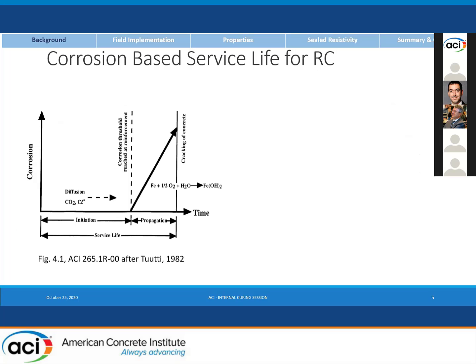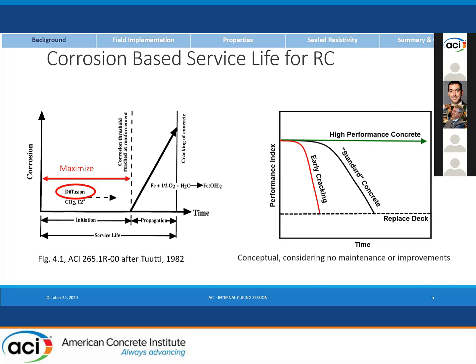So just to set the stage a little bit of what I'm talking about when I say service life, really I'm focused on corrosion-based service life. So we're going to be really primarily talking about extending the diffusion portion of the simplified model, where we have just an initiation stage and then a propagation stage for corrosion in reinforcement. And then on the other side of it, we actually do need to take care of the cracking. And so that's something where we're trying to avoid early cracking and really extend the performance.